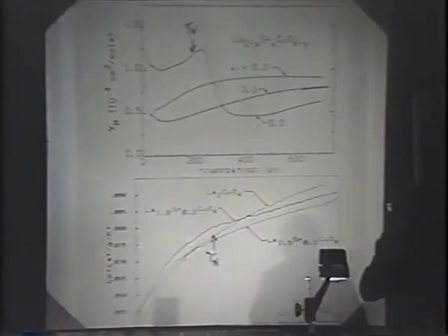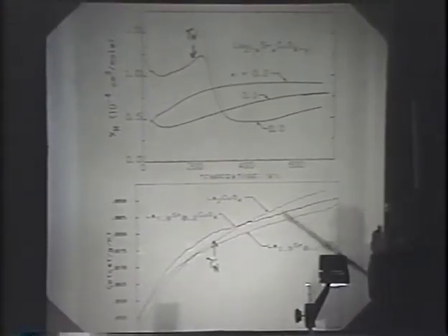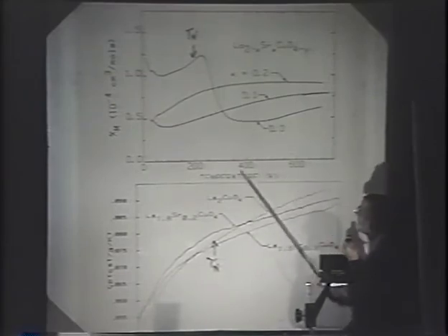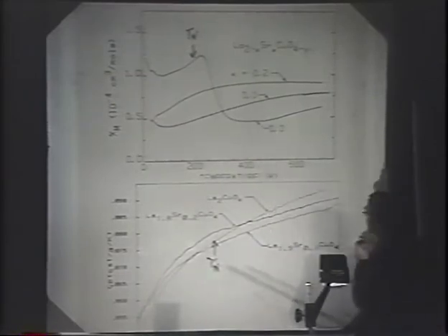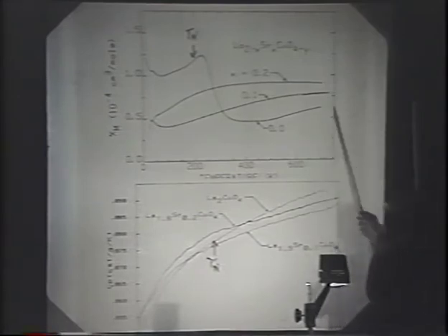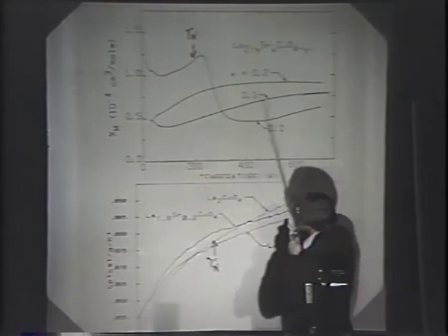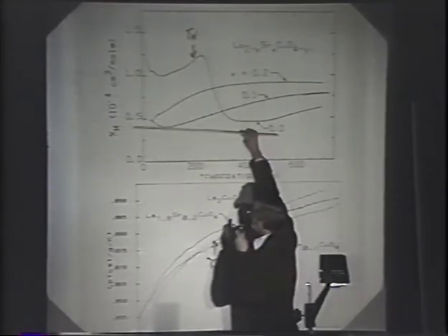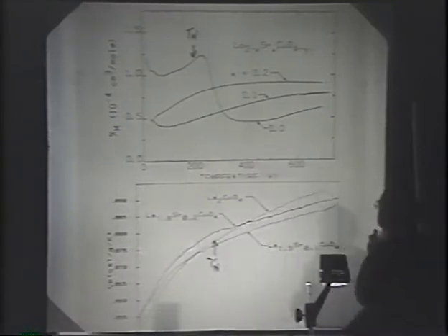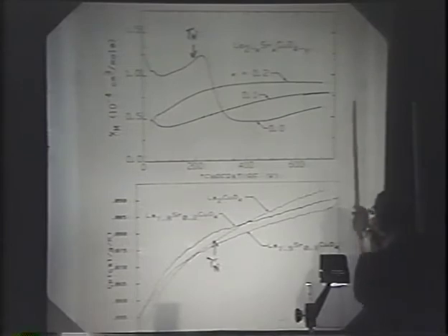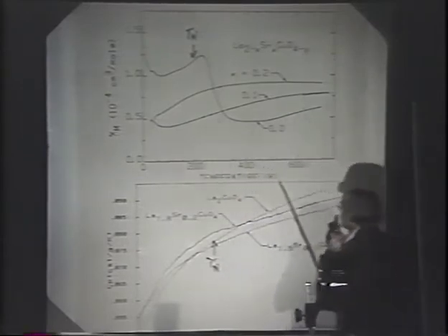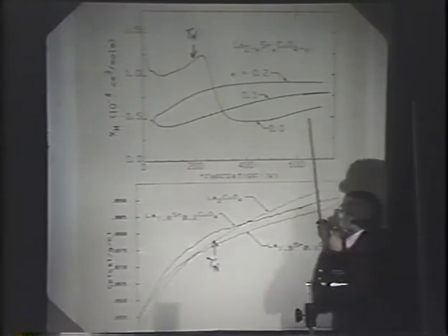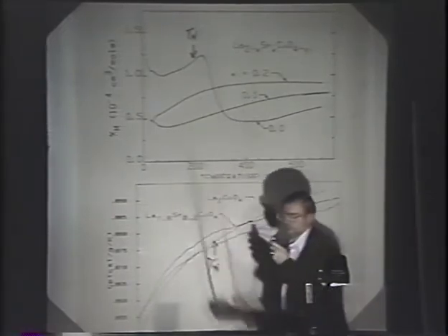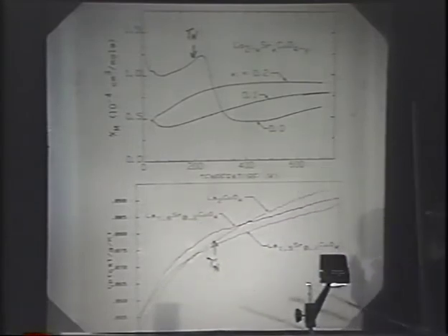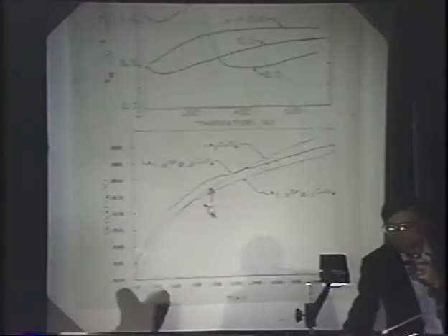Now, this is really interesting. Here's what happens when you add strontium. You go from a curve that looks like this to a curve that looks like this and then like this. But if you look at the high temperature data, you see a piece that's coming in like this in each of them, and you see a piece that's temperature independent. That is, one might do that decomposition. The shape of the curve suggests that you have a gap in the system, and the gap is decreasing with increasing x. The heat capacity at the transition shows no particular feature, which is a little surprising, actually.